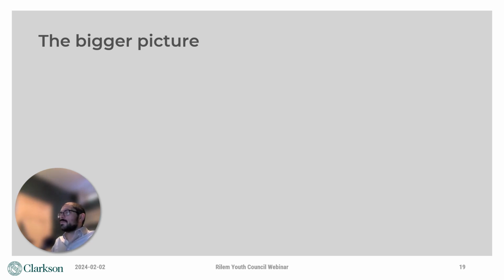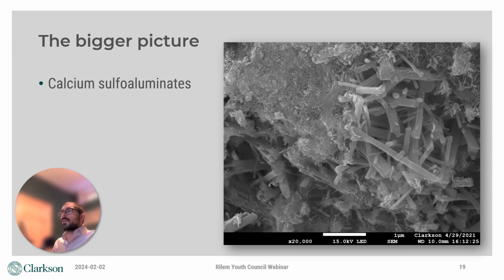But at this point, I think it's very important to acknowledge that our part of this work is small. There are so many other material technologies being developed that are just as promising, if not more promising, than lunar geopolymers. There are calcium sulfoaluminate precursors on the moon that could be used to make ettringite-based cements. This image shows the needle-like ettringite crystals that are the basis of these high early strength binder systems.